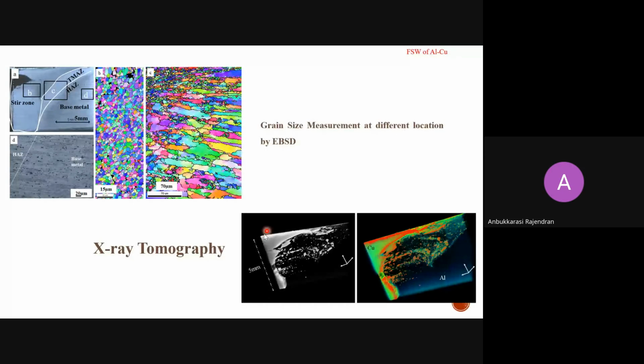So you have to slice your sample to that size, with some rough polishing on both sides. You need not have a mirror polishing or final polishing; some rough paper polishing is sufficient. Then you can place the sample in the machine. Using an X-ray source, it will do the mapping and give the 3D image, and we can get complete information about the particle distribution in the matrix.